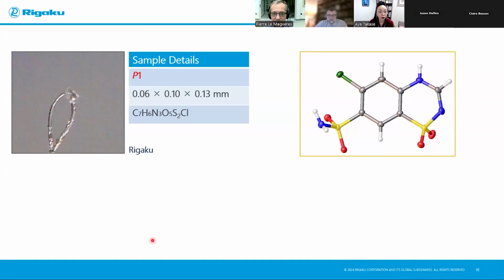So that first example is that of chlorothiazide. It is an organic compound. And I chose that example because chlorothiazide crystallizes in the lowest symmetry possible, P1. There is no symmetry in that crystal, not even the center of symmetry. So that means that there are no symmetry-related reflections. All the reflections are unique, which means that you have to collect all the reflections that come out of the crystal, and therefore, more reflections to collect means a longer data collection time. So that's why I chose that example.